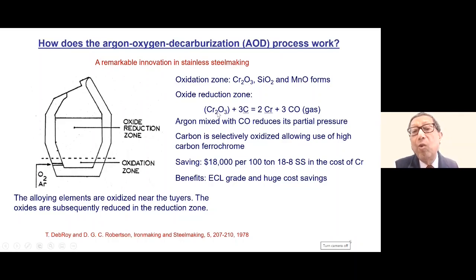So we don't lose chromium as chromium oxide anymore, but we recover almost all of the chromium in the bath. So we can selectively oxidize carbon without oxidizing chromium. And this is the ultimate in stainless steel manufacturing. And carbon monoxide gets diluted with argon gas. So because the partial pressure of carbon monoxide is reduced, the forward reaction goes at a very high rate and we recover all the chromium.